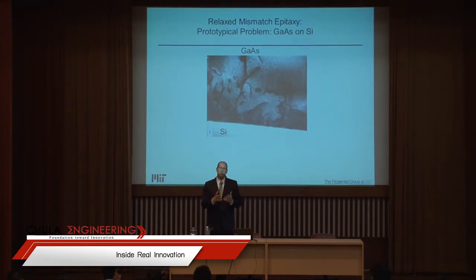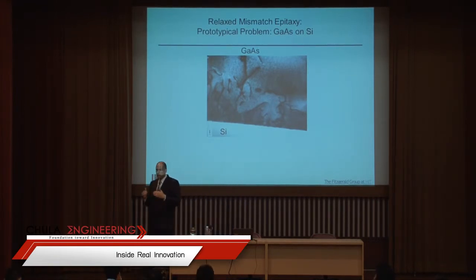Those black lines are dislocations. And the reason is that when you deposit gallium arsenide, the temperature required to seed off the silicon to make the same crystal structure is high enough that semiconductors go from a brittle stage to a ductile stage. So what happens is they're actually plastic. So you're depositing this one material on another, and because of the lattice change, they're forced to sit on top of the silicon lattice, so you build up huge stress as you grow.